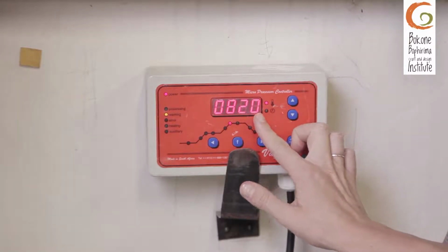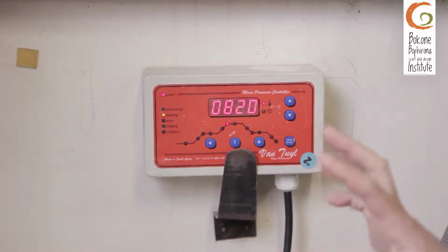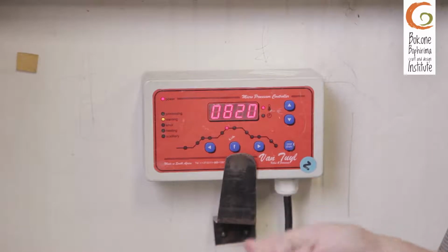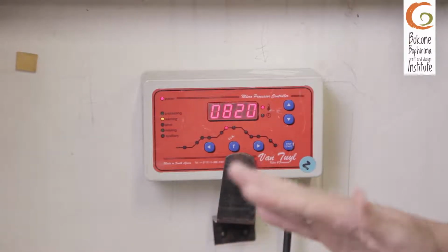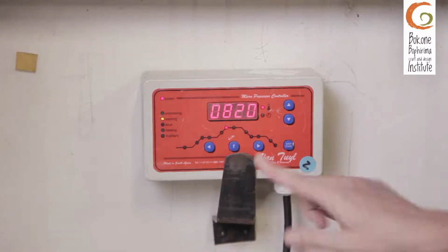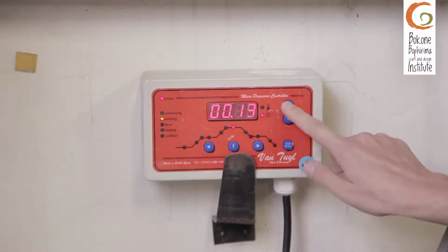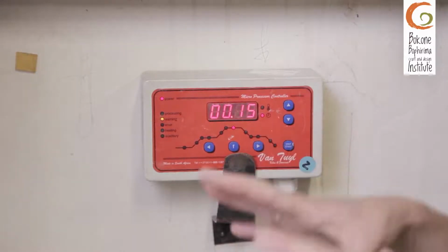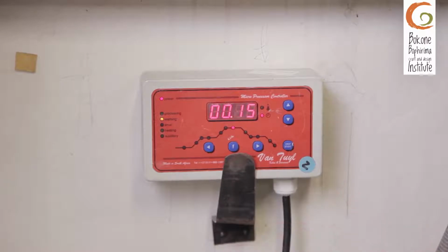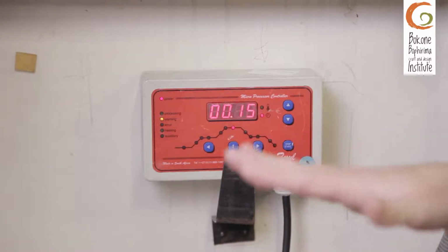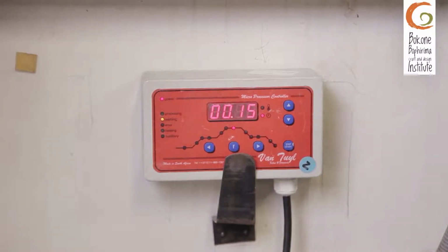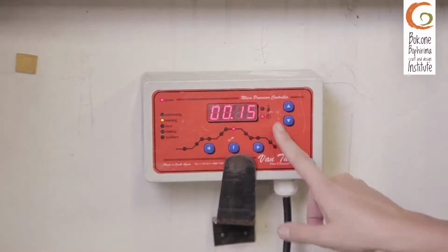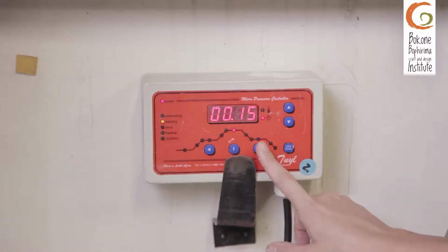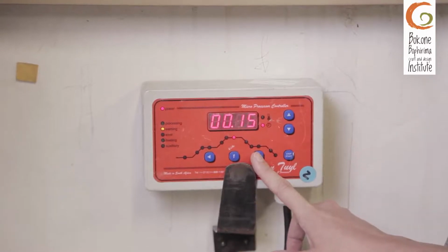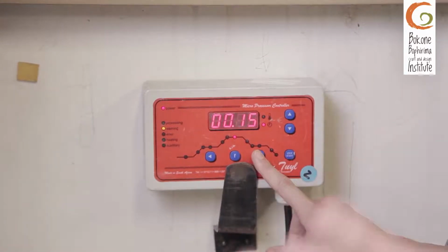And at 820 degrees, my glass will become soft and the edges will fuse to become one on the surface. So it will not be seen as two layers of glass anymore. I'm going to hold it there for 15 minutes to ensure that all my edges are soft and melted and that there are no air bubbles captured in between the glass. I then need to crash cool the process to be able to capture that glass in that moment.